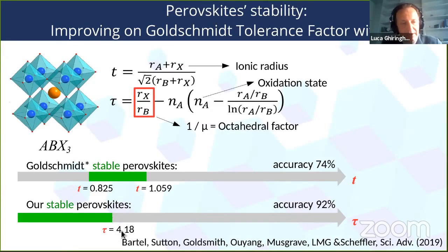But if we allow a little bit of leeway and we say that stable perovskites are here and clearly non-stable perovskites are here, the accuracy goes up. This is not just trying to dress up a little bit better what we have. We have an extra property here. We have a one-dimensional map and we have a continuous monotonic probability, decreasing from 100% probability of being a stable perovskite to zero probability, continuously in this range.